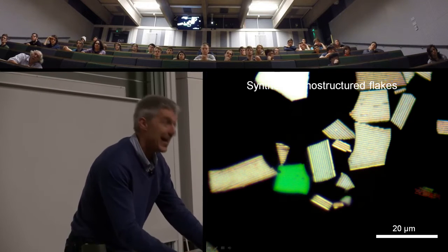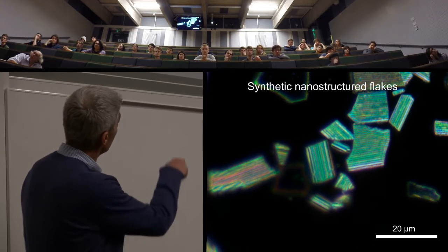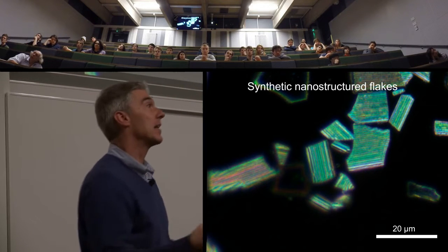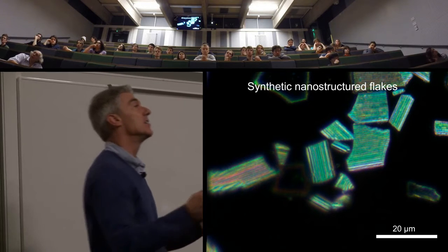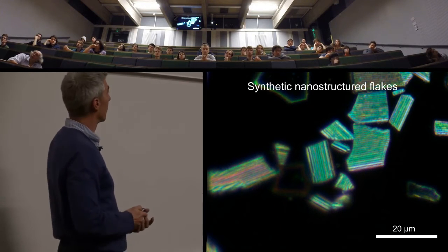That is an old style flake, flat. These are diffraction gratings. When we illuminate, not from above, which is referred to as bright field illumination, when we illuminate, here's the sample. Instead of from above, which is that picture, I'm going to illuminate from the side and collect light scattered straight up. That's referred to as dark field illumination. Look what happens. So not only does that disappear, because now we're not collecting at the mirror angle, but here we're seeing different colors because we're collecting a different diffracted order.